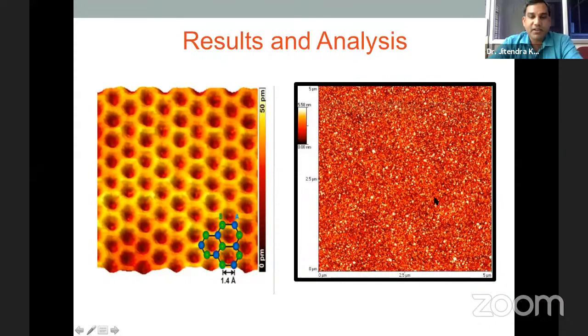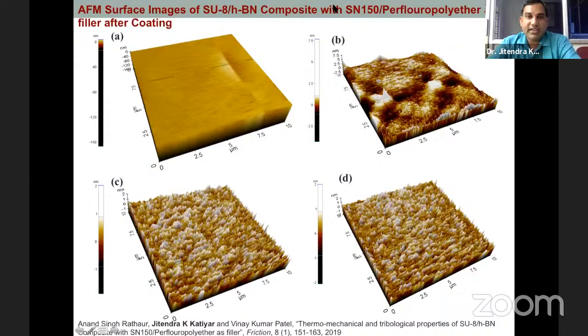For my own sample, I have tested this SU8 and hexagonal boron nitride composite with liquid filler, and this gives me the insight that whatever coating I have generated has nanotextures, because these nanotextures also play a very important role in wettability, increasing the hydrophobicity, and some other terms, because the contact area is reduced, due to which your frictional forces are also reduced. So these types of images help me in explaining why the reduction in the coefficient of friction happens, and what the basic phenomenon is in the reduction of friction and increment of the wear resistance.